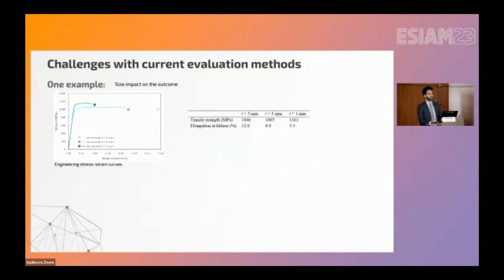We performed some tensile tests on this. And we could see that from 5 millimeter thickness to 1 millimeter thickness, there was 11% increase in strength and 73% drop in elongation. The same thing was done for conventional titanium. The difference was 2% and 7%, 1/10 of what we saw for AM.